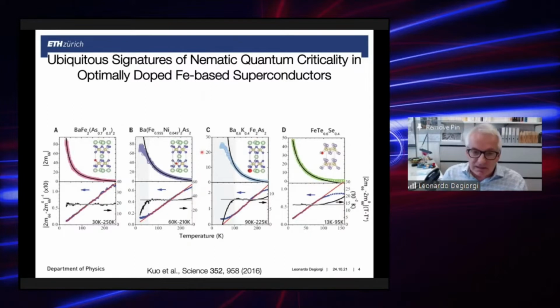Now, in the past, and I did report also at this conference on our previous investigation, we were focusing our attention on the underdoped regime. But recently, we moved our attention to the optimally doped regime in order to investigate the impact of nematic fluctuations, because optimally doped materials are always in the tetragonal phase, on the charge dynamics, which actually images the absorption spectrum related to the electronic band structure. And this over a rather broad temperature interval, which also extends to temperatures in the superconducting regime, so deep into the superconducting dome, as far as the phase diagram is concerned, which is a regime that is not accessible with elastoresistive type of investigation.